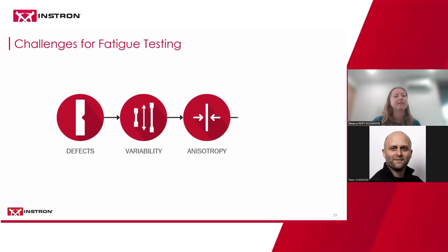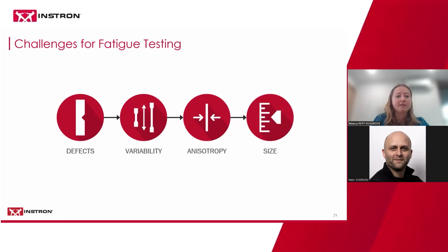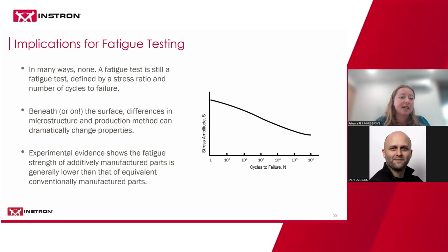With these different methods of creating a part, we see different challenges when it comes to fatigue testing. Throughout this talk, I'll touch on four of these: the effect of defects, variability, anisotropy, as well as size. Don't worry, I'll define all of those as I get to them, and I'll talk about their general implications for fatigue testing. Firstly, what I want to clarify is that in many ways, there are none. A fatigue test is still a fatigue test. It's still defined by a stress ratio, which you might see on the y-axis on the right-hand side, and a number of cycles to failure, which you'll see on the x-axis on the graph. And we can still build up an SN curve based on fatigue for additively manufactured parts. So it's the same in that respect in terms of definition.